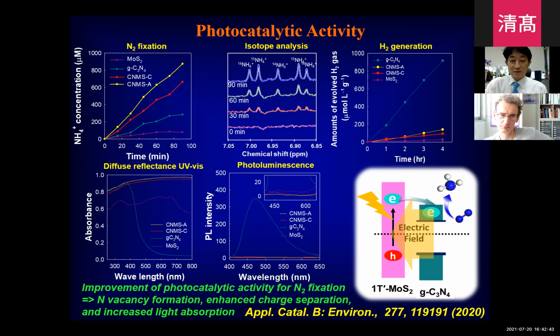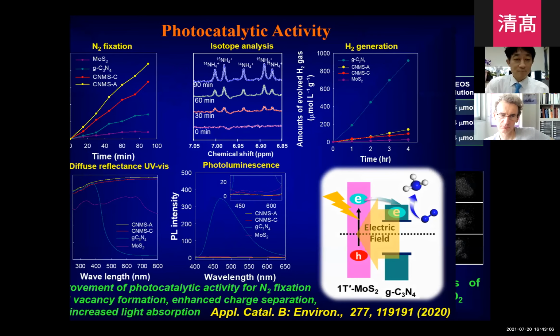We believe that the main reason for the improvement of selectivity for nitrogen fixation is the generation of nitrogen vacancy during the hybridization, because the formation of nitrogen vacancy is very effective in the enhancement of the adsorption of the reactant nitrogen molecule to the catalyst.